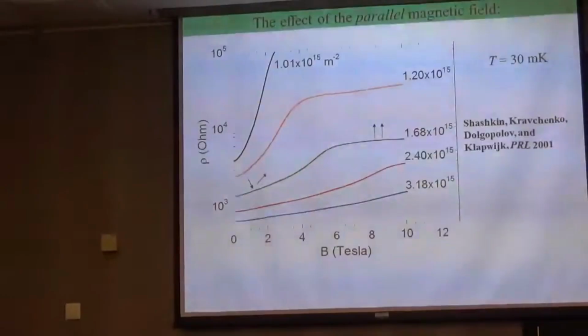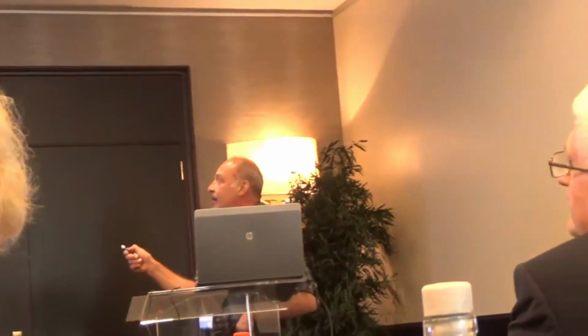Next, suppose we now apply a magnetic field parallel to the interface. So it doesn't induce any orbital motion, it only couples to electron spins. So here spins are random when the field is close to 0, and then they become aligned. And you can see what happens to resistance. It grows, and then it saturates. So it looks like once spins are saturated, the field has done all it could do. Nothing else can be done. It doesn't change anymore. The data were taken at very low temperature, 30 millikelvins, approximately 100 times lower than it is in open space.